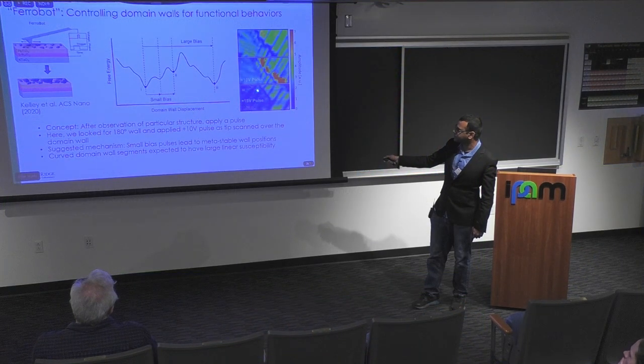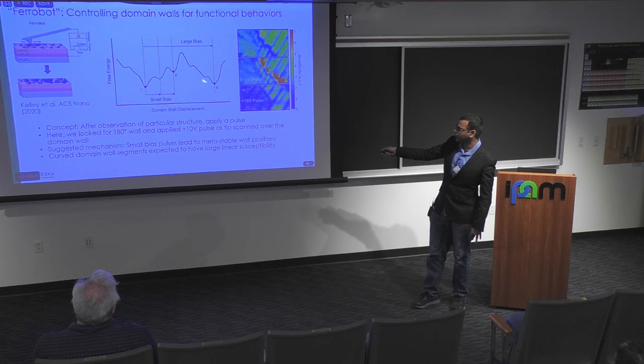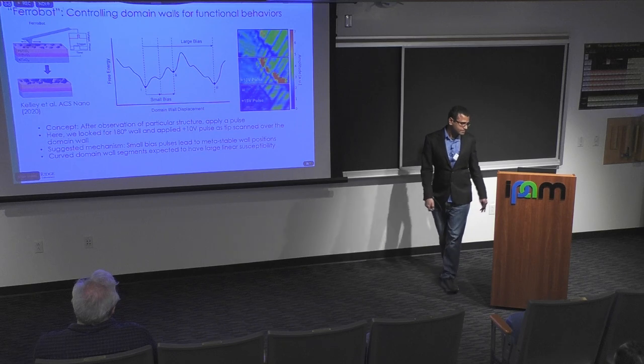If we use larger voltage pulses, you can see that this region of high response goes away. The reason is that for small biases, you might be able to move the domain wall in this free energy landscape to a higher energy position. But for large biases, you would expect it to relax back to a lower energy state because it has overcome this large potential barrier here. And that's exactly what we see.